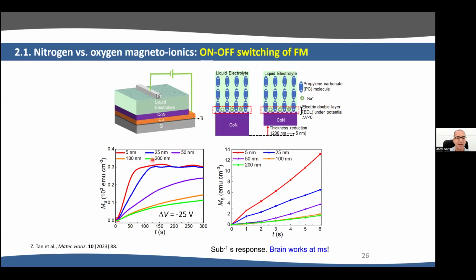And what we did is to decrease the thickness from 200 nanometers to 5 nanometers. And here you can see for 200 nanometers that, applying this minus 25 volt, it takes about 5 minutes to get a significant magnetization. But with 5 nanometers, everything happens in less than 1 minute. And actually, if we zoom here at the first points, shown here on the right, you can see that after 1 second for 5 nanometer cobalt nitride, we already induce some magneto-ionic effect. So basically what we have achieved here is going from about 1 hour in our original experiment of cobalt oxide to less than 1 second, changing from cobalt oxide to cobalt nitride and decreasing the thickness to 5 nanometers.